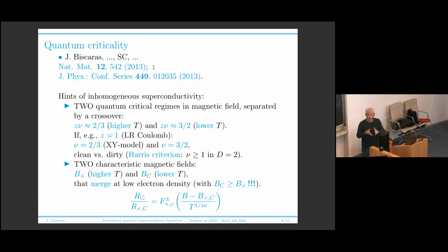So you start from the superconducting state, you increase the magnetic field, and you turn the superconductor back to the metallic state by means of the magnetic field. Now, this transition seems to occur in two steps, at least in the region where the density of carriers in your cluster is very large. And what is interesting is that you have two regions where you have two different scalings for your data. I will show the curves in a while. One scaling is with the dynamical exponent times the nu exponent equal to 2/3. And the other is with 3/2. And those two are clearly different.